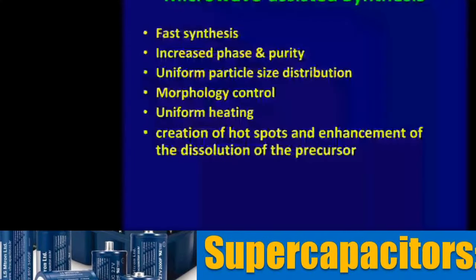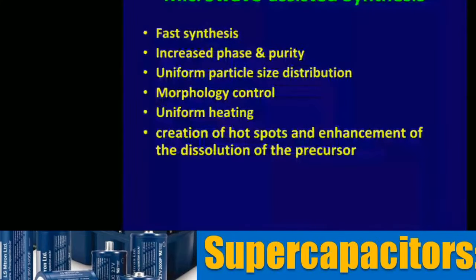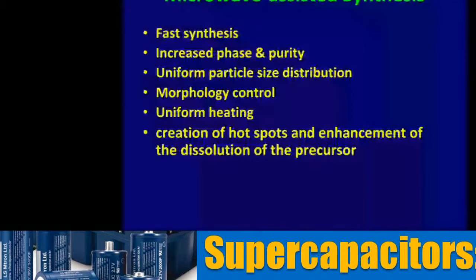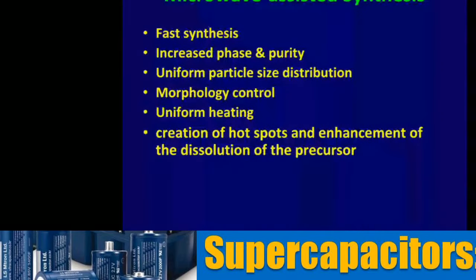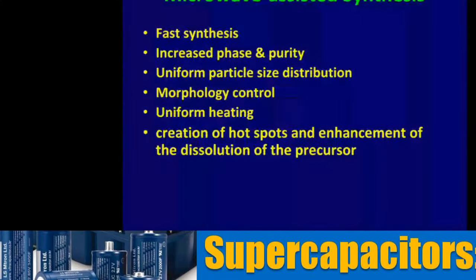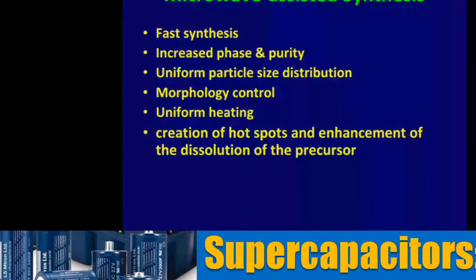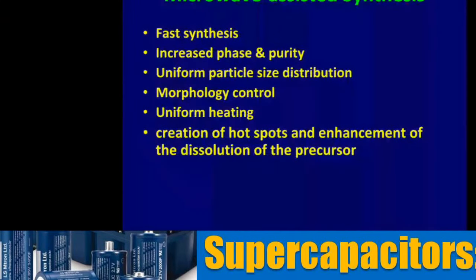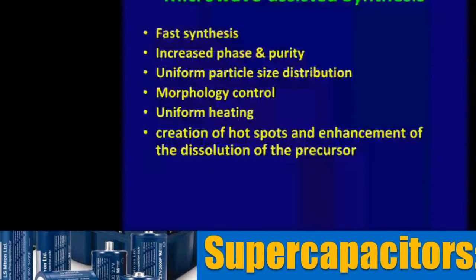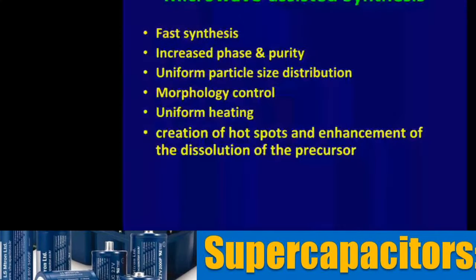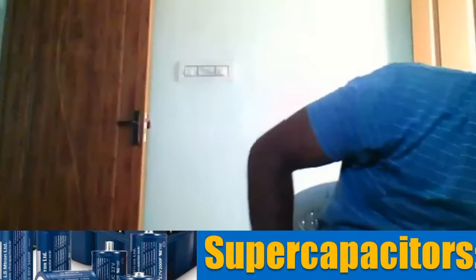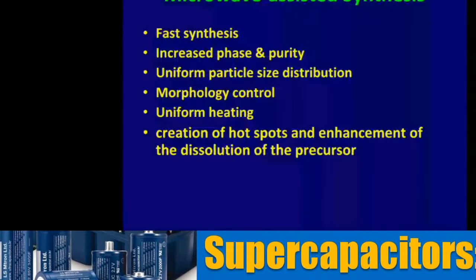The other interesting aspect I would like to wind up with is the microwave assisted synthesis. Microwave assisted synthesis is very interesting for a simple reason: it is a very fast synthesis. We could prepare nickel oxide through microwave assisted synthesis in 5 minutes. You can see how fast the process is. The advantage is increased phase purity and a very good particle size distribution. Why? What is the reason for this? I do not know whether people have tried dry frying of apalam in the microwave oven.